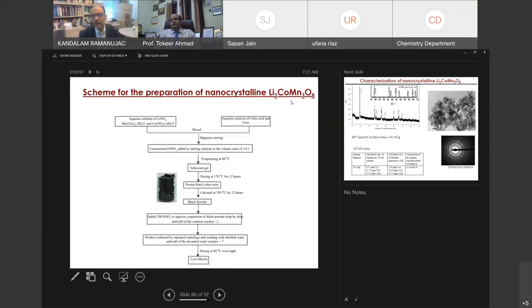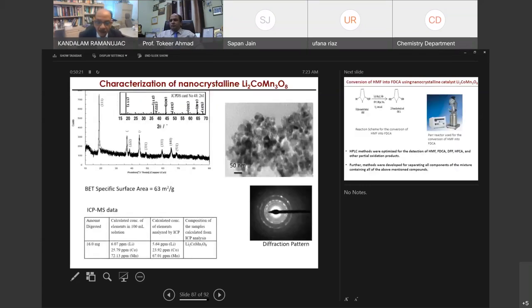Our target composition here is to make Li2CoMn3O8, which is almost like a double spinel compound, to use this compound as the catalyst. So it took us a while to make this compound, and we were able to confirm the structural identity by X-ray diffraction, and the particle sizes were almost 20 to 30 nanometers. We have done electron diffractions.